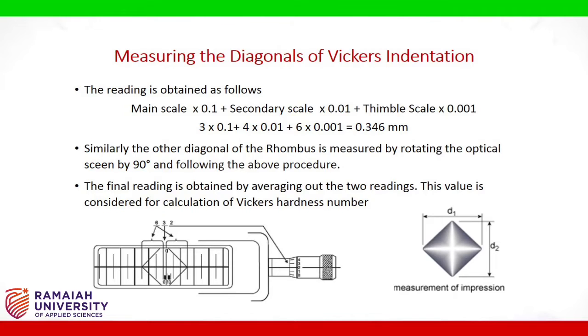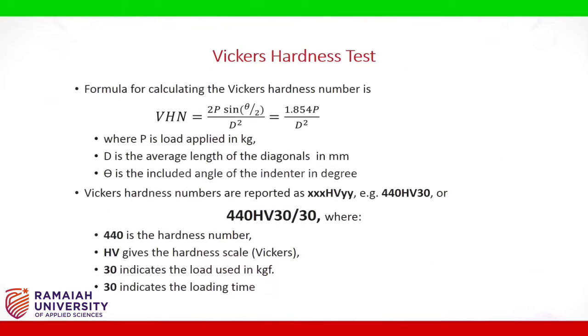Similarly, the other diagonal of the rhombus is measured by rotating the optical screen by 90 degrees and following the above procedure. The final reading D is obtained by averaging out the two readings. This average value is now considered for calculating the Vickers hardness number. Vickers hardness number is calculated by using the simplified formula VHN is equal to 1.854 P divided by D square, where P is the load applied in kgs and D is the average length of the diagonals in mm, and theta is the included angle of the indenter in degrees.